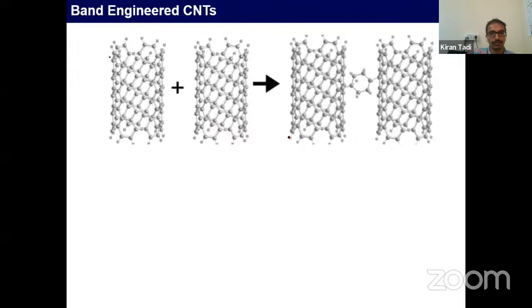So without changing the electronic properties of these CNTs, we made a benzene C-C bond to bind these carbon nanotubes using Suzuki coupling. One of the interesting things is these CNTs are highly stable inks, and you can get these covalently connected carbon nanotubes using this method.